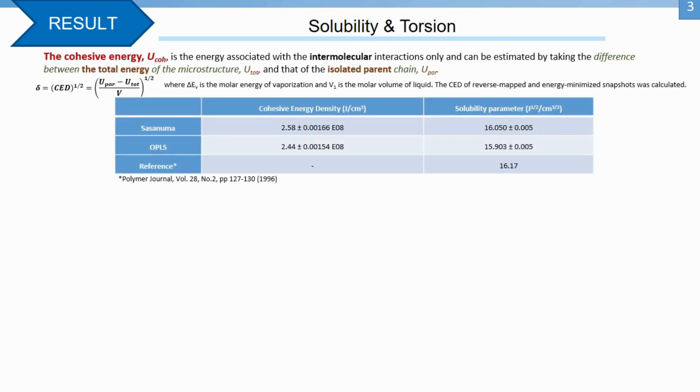To validate our polymer model, first we calculate the solubility parameter. Our results are very close to experimental data and are irrespective of two RIS models used to generate PPO structure.